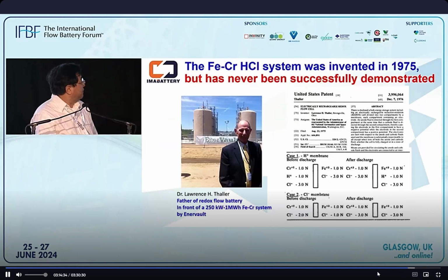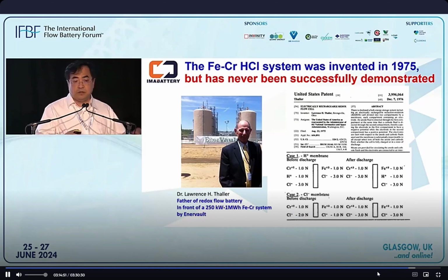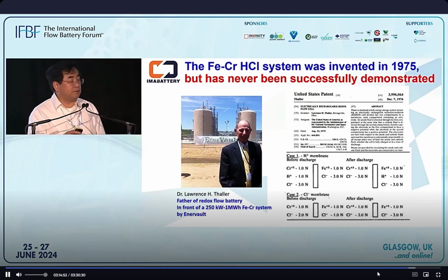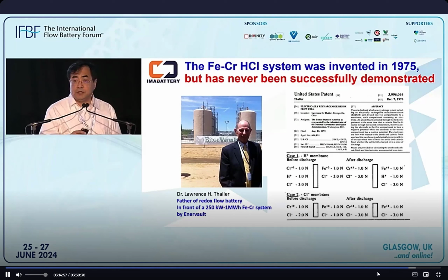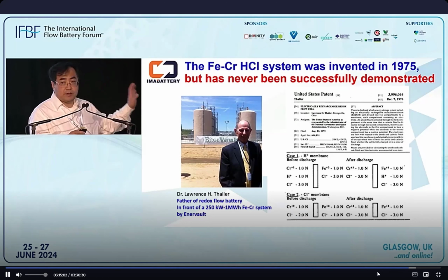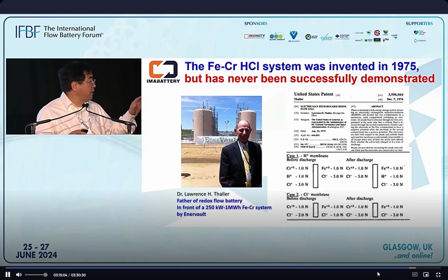That's the famous Larry Thaller from NASA, and he invented this technology about 50 years ago. Actually, this one never been successfully demonstrated in the past years, although many companies tried. The major issue with this one is that chromium 2 and chromium 3 are electrochemically not very active, and then generate hydrogen, capacity decay, then the system just is dead.